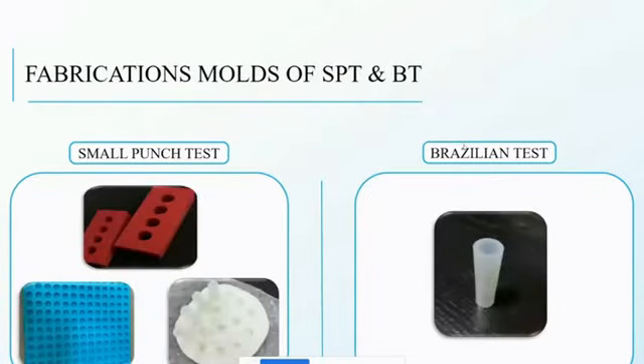For the fabrication of the mold, we got some difficulty to have the mold for the small punch test and the Brazilian test. We try different ways. We use the 3D printing machine to make the sample for the small punch test. Also, we got some manufacturer-made silicon molds. Also, we try to manufacture our own mold for such kind of samples. For the Brazilian, we have it already. We just put the sample inside and cast it inside this one, and we cut it after it's dry and cured to have it for the test.